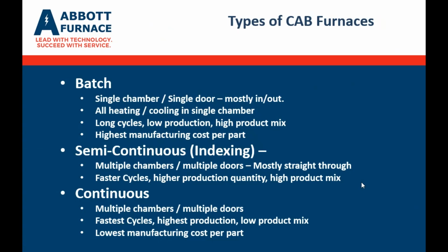versus some of the continuous processes. Batch may give you long cycles. It's not generally looked at as high production, although with small parts, some of the sizing can produce fairly high production numbers. And a batch furnace does allow a high product mix as well. The ones we're looking at use convection, where we're mixing up the atmosphere, which allows a high product mix for somebody running various different products at lower volumes.